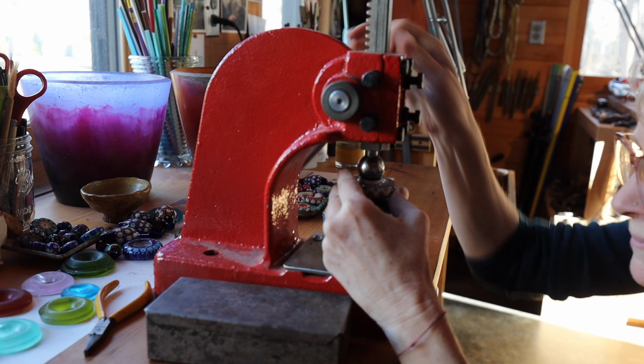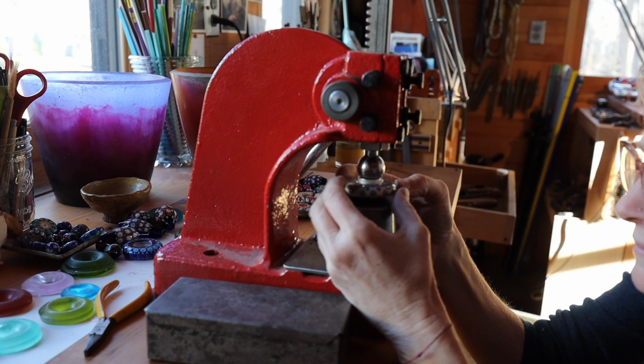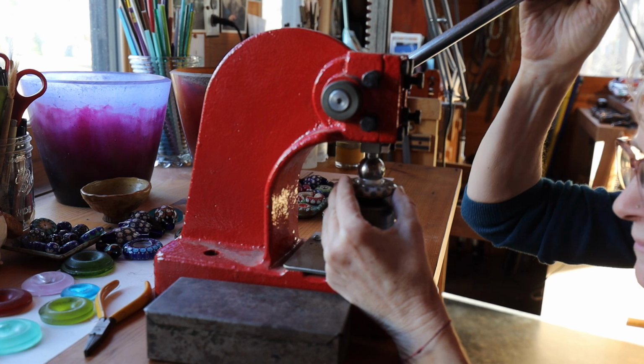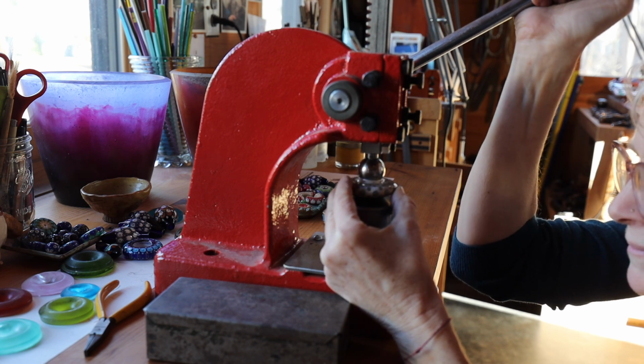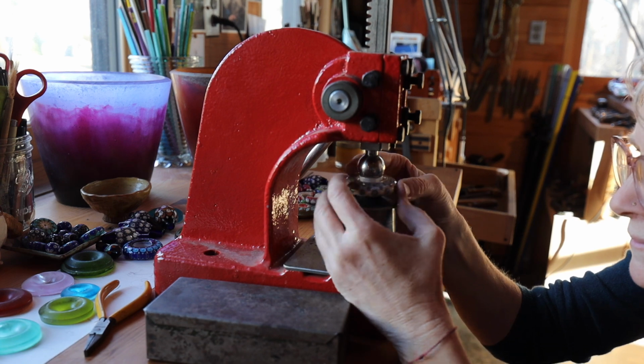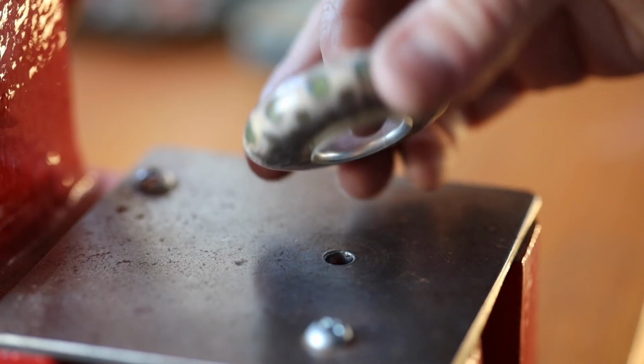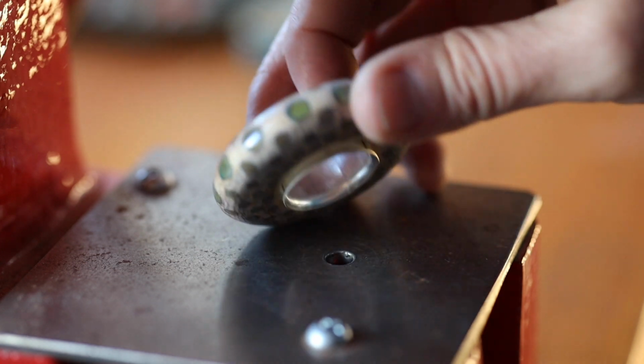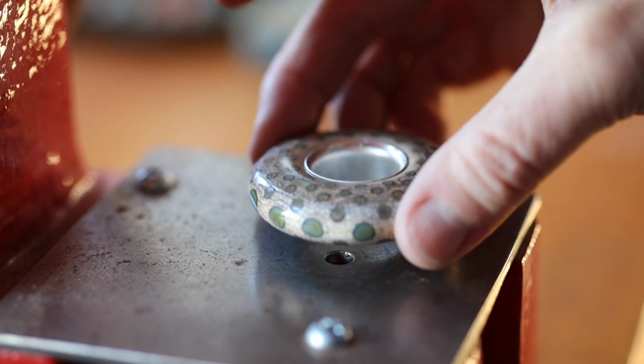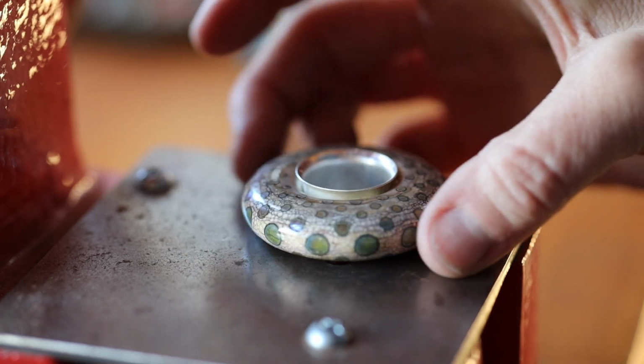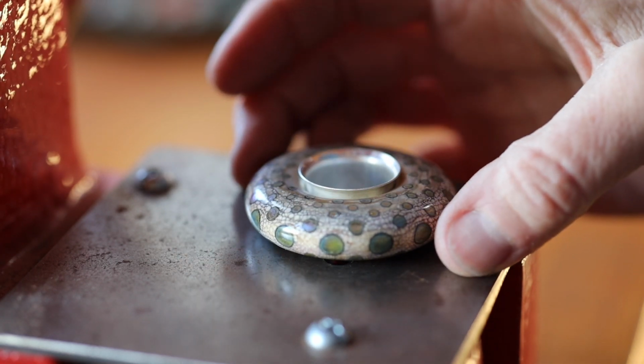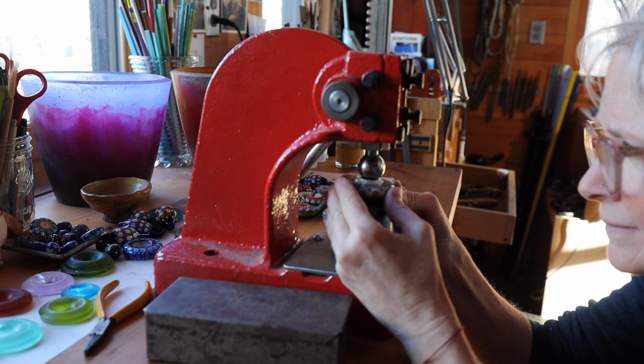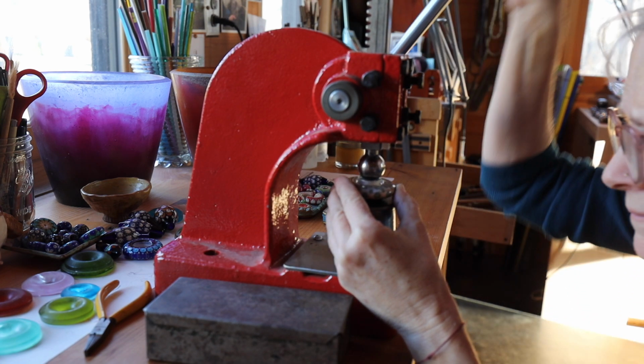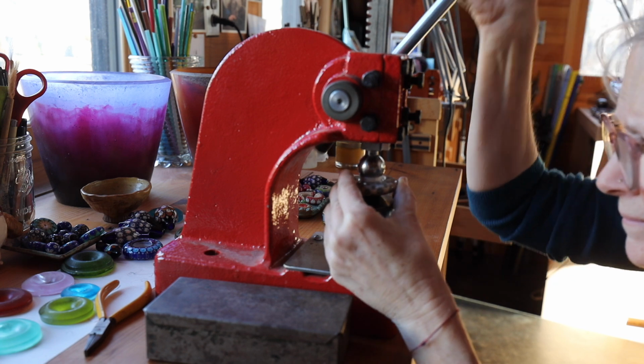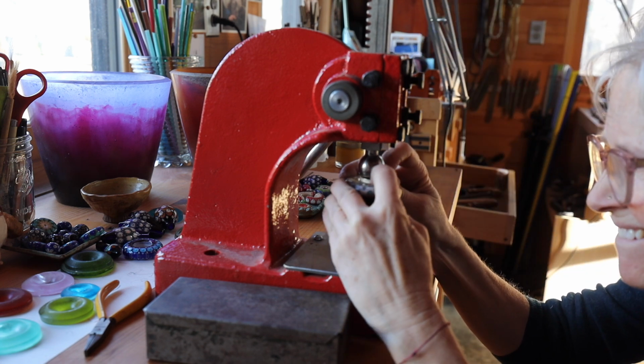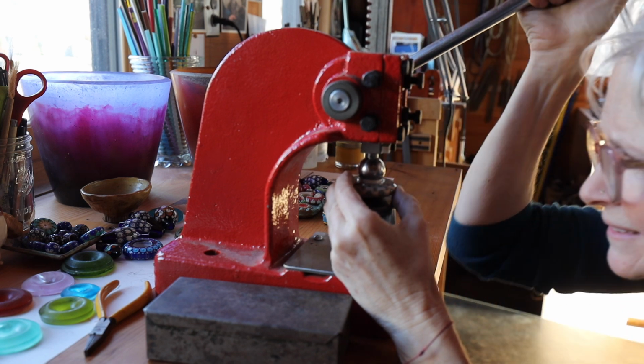In my experience, working slowly is the key. Although it seems like these tools can do the job in just a couple moves, the slower I ask the metal to move, the less likely it is to tear. So I also like to work in this way, so I don't mistakenly drop the glass on the floor, or even worse, crack the glass by pressing too much or too quickly with the press. I've made all of these mistakes. So again, working slowly is really the key.